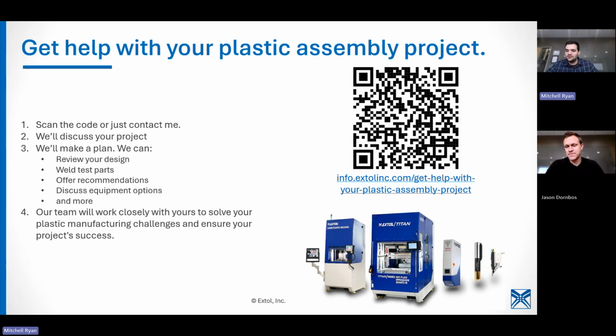What's the weld failure rate? It's very dependent on the customer's parts, but with a well-optimized and well-controlled process, within reason, we're not expecting that all of the parts coming into a plastic welder are perfect. We know they're not. They're plastic. And as we mentioned in a webinar not too long ago, plastic be plasticking, and it warps like crazy, and there are lots of inconsistencies. But it's reasonable to expect a scrap rate of 1% or less.